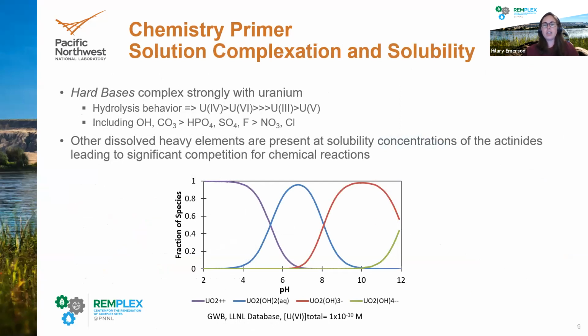And so moving along, just to help drive home the increase in hydrolysis with pH, this is a figure showing uranium-6, and you can see that above pH of about 5, uranium-6 will be present as hydrolysis species in solution. And then for uranium-4, hydrolysis begins even lower, around pH 2. But overall, uranium often complexes with hard bases, primarily including hydroxide and carbonate in the natural environment, but also including things like phosphate, sulfate, and fluoride, and less so nitrate and chloride.